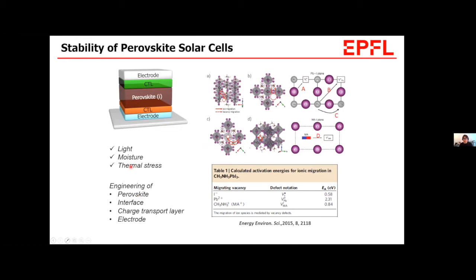So now efficiencies of perovskite solar cells are high, but what we still need to improve is stability of perovskite solar cells. So perovskite material or device can be degraded by light or moisture or thermal stress, these external stresses. To keep the perovskite solar cells stable, the engineering of the components consisting of the cell is essential. One of the main reasons for this weakness against these external factors is that perovskite is based on the ionic bond. So the formation of ionic defect is inevitable, and the ion migration occurs, and it should be managed.